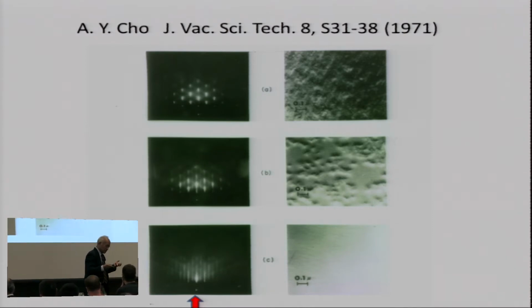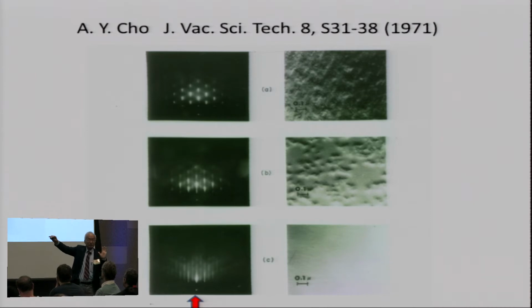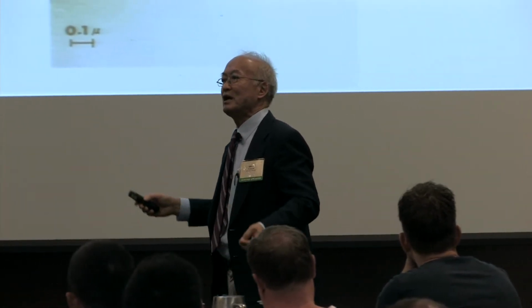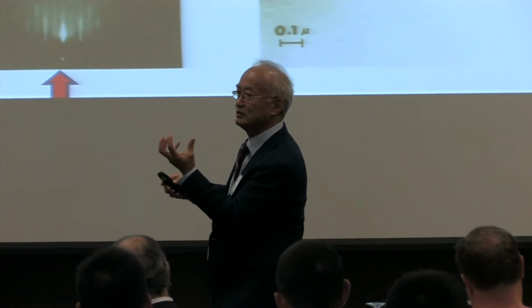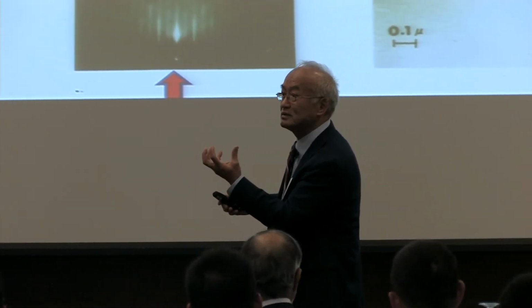The surface has little tiny hills and valleys. The electron beam, the diffraction beam, coming onto the surface at a grazing angle, had to penetrate through the protuberances on the surface. The three-dimensional Laue condition has to be satisfied. The three-dimensional Laue condition gives you spot diffraction in the reciprocal space.